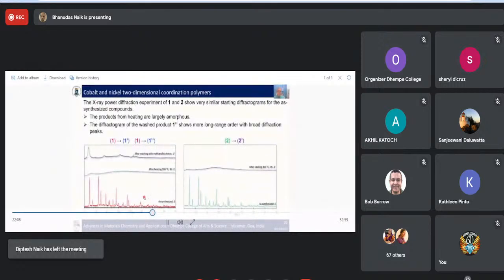And here we did the X-ray powder diffraction. You can see that both compounds, the cobalt compound and nickel compound, have diffractograms which look really quite nice, and they're actually really similar here. And if you heat them up to 300 degrees, you can see you have basically an amorphous compound here, where you have a very small amount of long-range order. These small peaks here are long-range order, which you can get from if you do a PDF analysis.